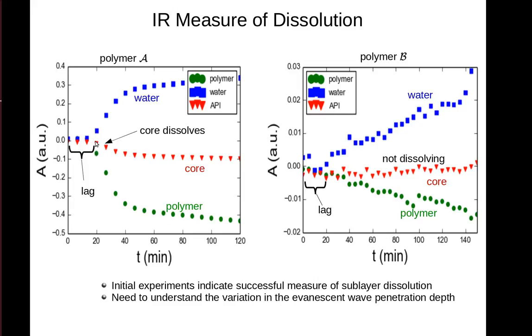And for Polymer A, we see a small but very noticeable decrease in the spectral intensity of the core material, specifically the API, suggesting that we are dissolving the API, and again it is moving through the polymer film up above, well above the polymer film, out of reach of the evanescent wave.